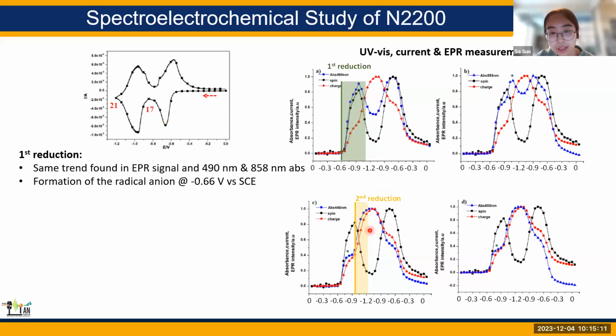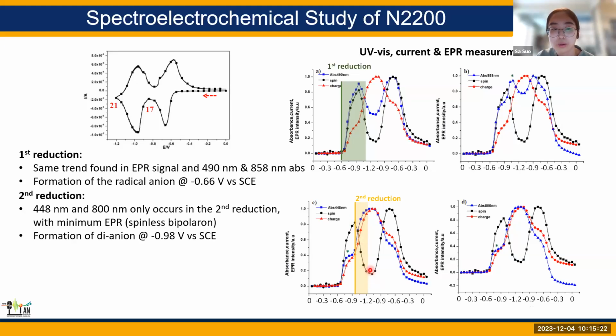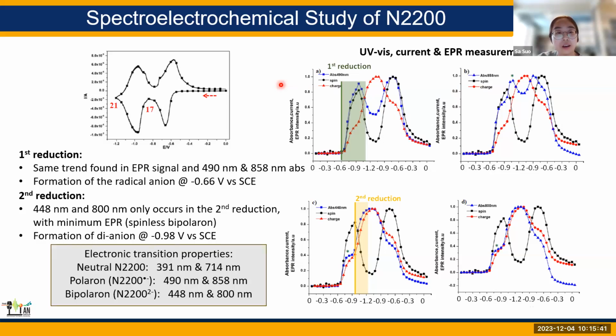For the second reduction, they saw increasing blue shifted absorption. Meanwhile, they saw the spin decrease to 0.2. So the minimal EPR tells them basically it is the formation of the dianion for the second reduction. So this is the current understanding of the spectroelectrochemical doping of N2200. And I summarize the electronic transition properties for the neutral, polaron, and bipolaron peaks.